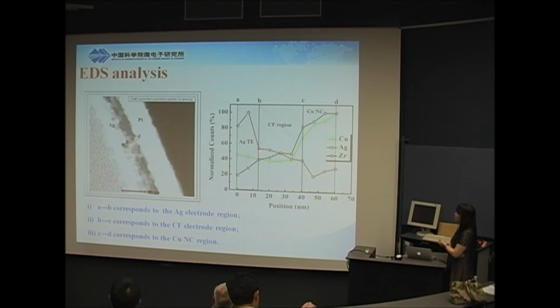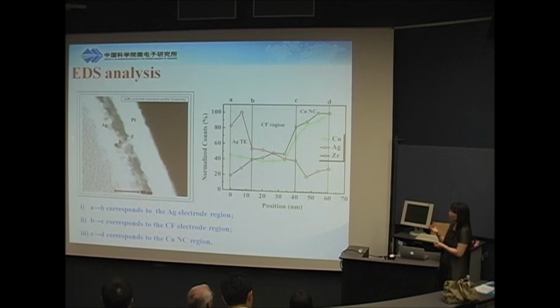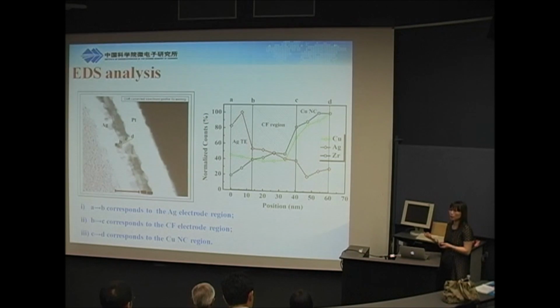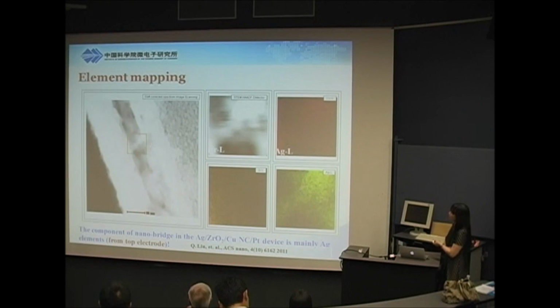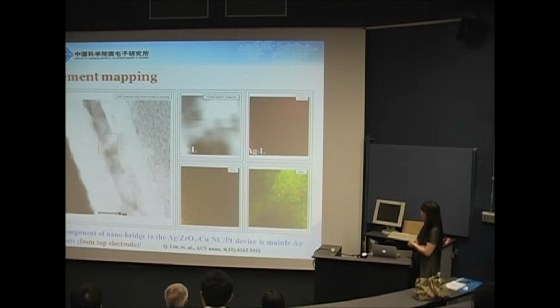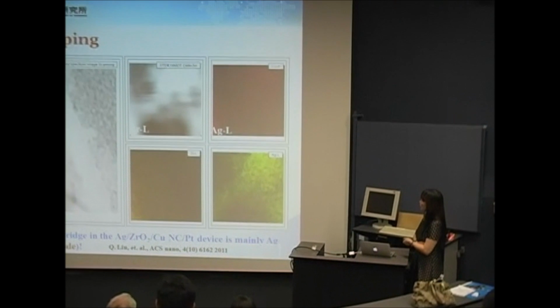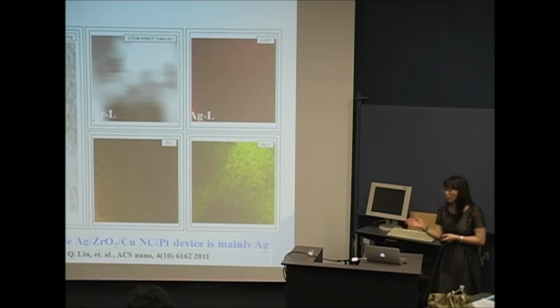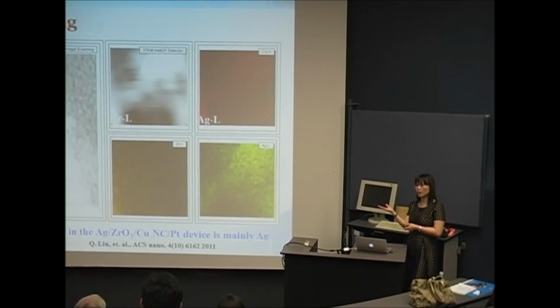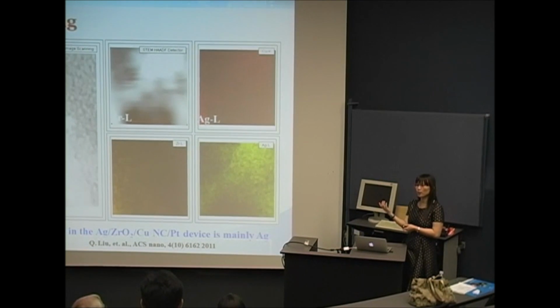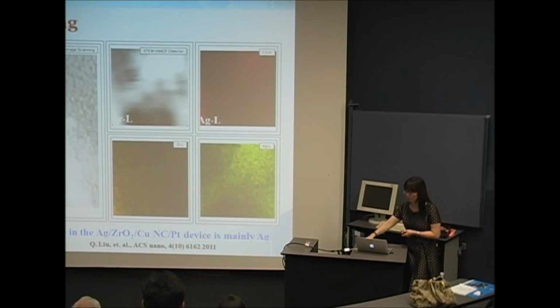We can see that in this filament area there are copper, zirconia, and also silver. This sample is hosted on a copper ground. So the electrode here does not use copper, just silver. Because if we still used copper as the electrode, we could not distinguish which comes from the background and which from the real filament. So we also did some mapping there. Here you clearly see that in this filament area there is silver, and the signal is very strong. The other area is very dark. For the other materials, zirconia and copper, the distribution is very uniform. So this confirms not only that the filament grows around this nanocrystal, but also that the filament consists of the same material as the bottom electrode.